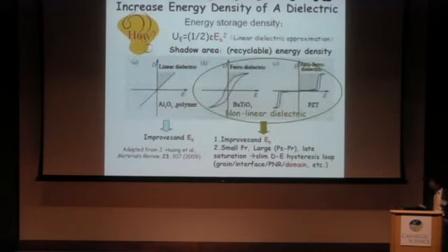So let's go back a little bit about the dielectric. We know for a linear dielectric, for example, alumina or linear polymer, the energy density stored in a linear dielectric capacitor is just the area between the dielectric displacement and electric field. It's linear, right? You can use a very simple equation to calculate that. But for nonlinear dielectrics, for example, ferroelectric or antiferroelectric, they're different, right? So the key, like I just mentioned, to improve the recyclable energy, that's the area outside of the loop, is to have a very small remnant polarization and a very large saturated polarization.